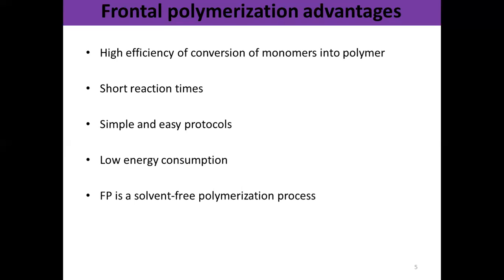First, high efficiency of conversion of monomer into polymer. Generally, the conversion is more than 99%. Second, simple and easy protocols. Third, short reaction times. Frontal polymerization generally requires only a few minutes to convert the mixture of monomers, while classical polymerization techniques often need long reaction times. Fourth, low energy consumption. The external stimulus is only applied until the propagation front is formed. Fifth, frontal polymerization is a solvent-free polymerization process.